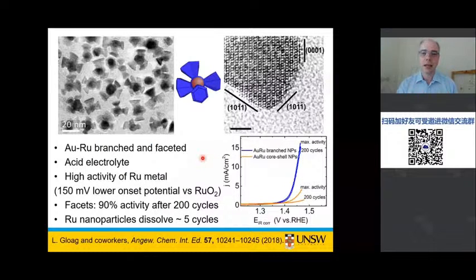So we set about designing synthetic methods and synthetic approaches where we could make some branch particles, because they should have a high surface area, and also branch particles with these low index facets. And these are the particles that we ended up making. So if you have a look, this is a TEM image of the particles.